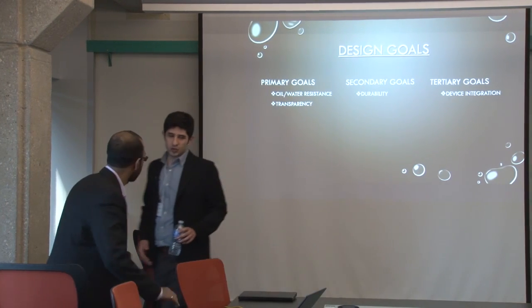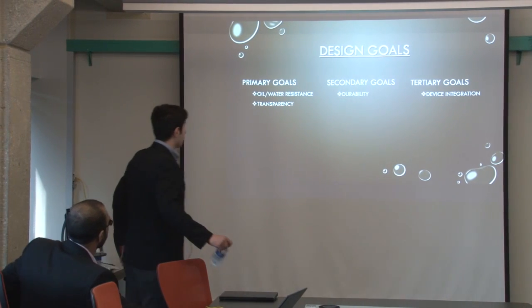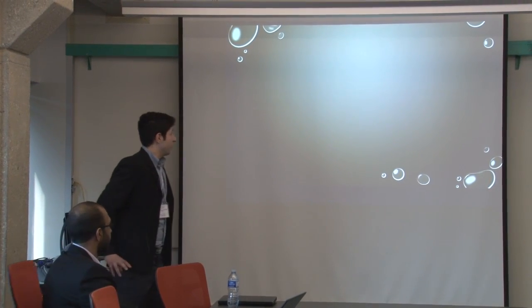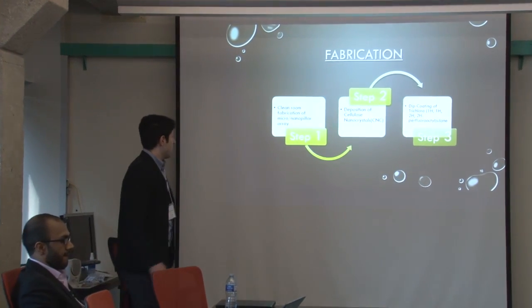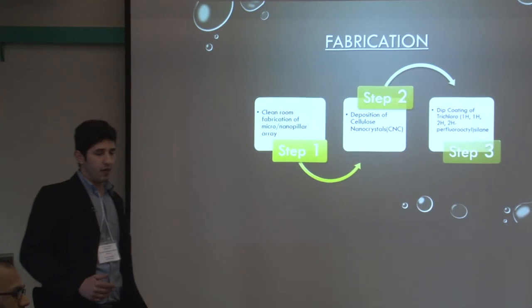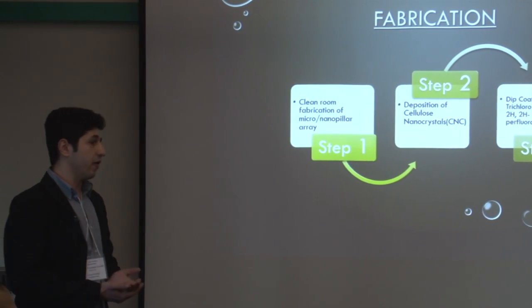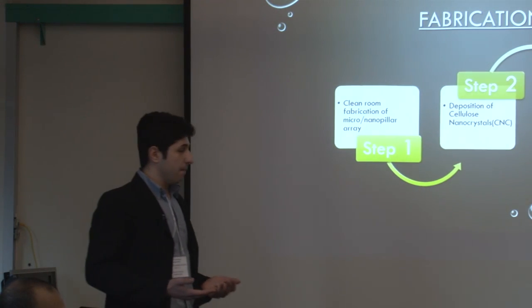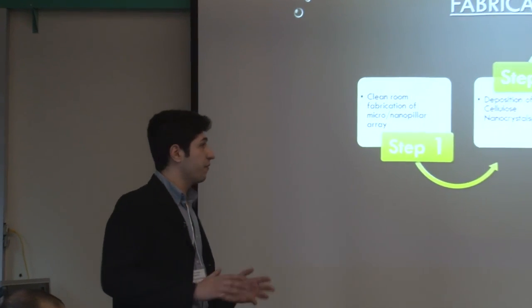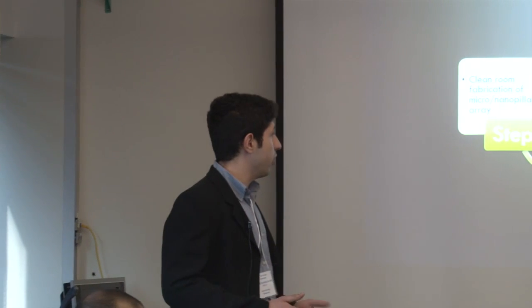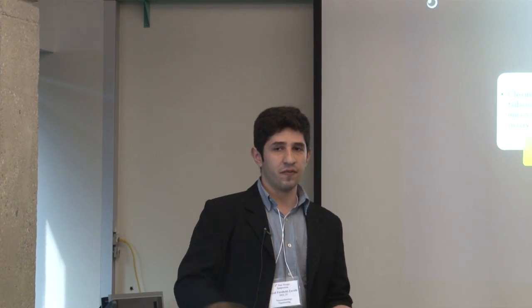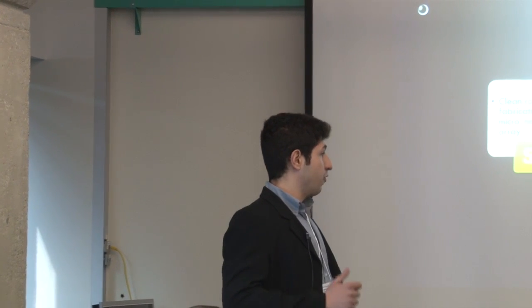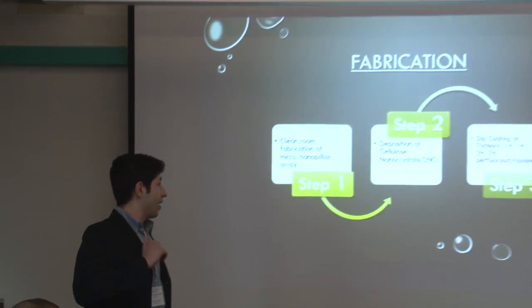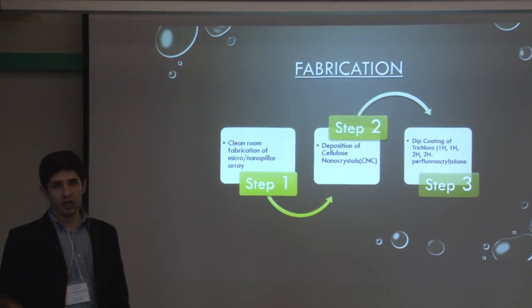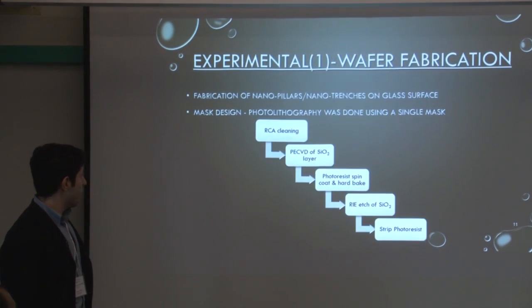So in order for us to achieve these goals, we need to go through a series of fabrication processes. What we did at the beginning was create these nanopillars on top of our glass substrate. And then in order to protect those nanopillars from breaking off and to add extra support, we decided to deposit several layers of cellulose nanocrystals, or CNCs. And finally, to reinforce the hydrophobicity of the surface, we're going to treat the surface with a low surface energy material at the end.